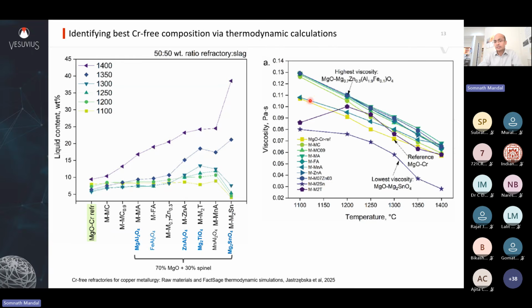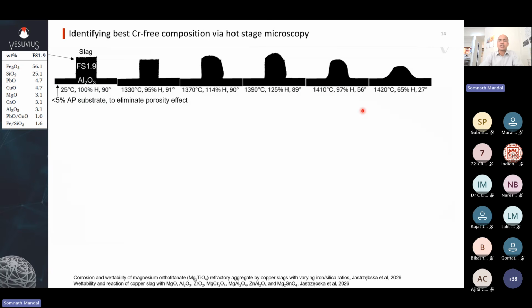The beauty of this software is that you can also predict viscosity from this, and from there we realized that if we are able to have a spinel with zinc aluminate and a small amount of iron in solid solution, then you get a very high viscosity slag that is always beneficial for improving corrosion resistance. So from these theoretical insights, a series of experiments were started.